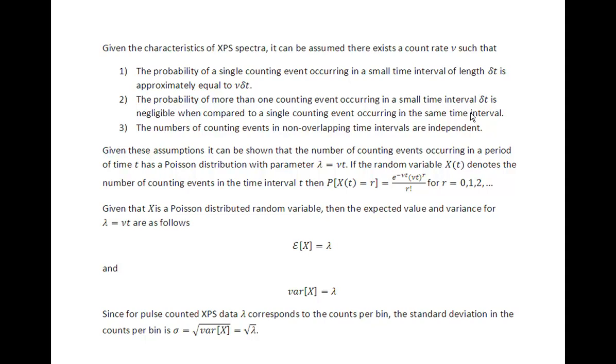If the count rate is too high then our detectors will saturate, so we have to make sure that our detectors are not saturated, otherwise quantification will be difficult. We necessarily measure our data under this regime, so the second condition is satisfied.